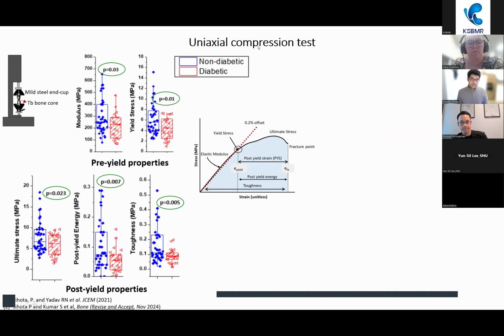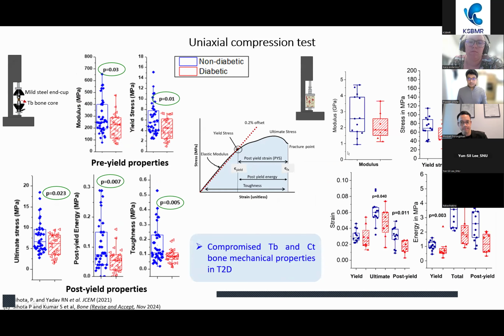The mechanical property test done with compression says the following. We use a typical stress-strain curve, and the pre-yield properties are determined below the yield point, and above the yield point, all post-yield properties are determined. It's a standard way to determine mechanical properties. We found that both pre and post-yield properties are lower in the diabetes group. Whereas in cortical bone, we did not find a difference in modulus or yield stress, but ultimate stress, strain, and energy-related parameters are lower in the diabetes group.